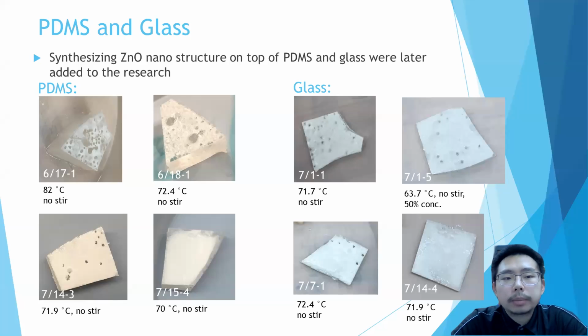Later on, PDMS and glass samples were introduced to research. The same synthesized method as the 3D printed resin part was used for these two new materials as well. One big problem we found with these was there were many air bubbles forming on top of the samples and on the side of the sample, especially for the PDMS.